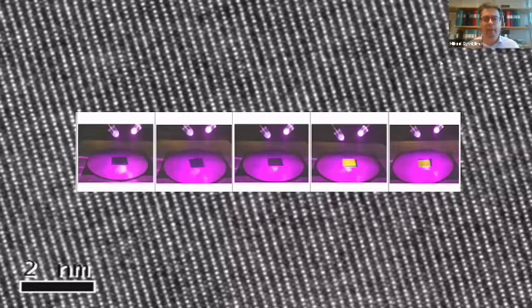And here you see some images. On the left side, on the top, you see two near UV LEDs, and they are emitting light to the silicon carbide. On the left side here, you see no emission at all, so the balance was not proper. Then we modified things, and on the right side you see that there is more luminescence. This is one of the layers. This is the warm white. There's luminescence from one of the samples. And if we try to optimize further, we are out of the range. So there is an optimum at some point where there can be luminescence from silicon carbide. And this is at room temperature. So it's not theory, it is actually something which is happening.